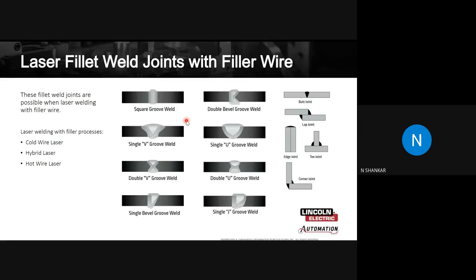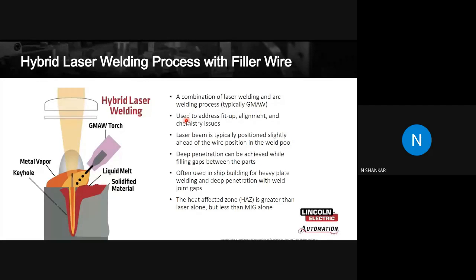You can do a cold wire laser or a hot wire laser with hybrid laser welding. When you say cold, you use a GMAW torch and you feed a wire. Conventionally it's called GMAW hybrid laser welding, where a combination of a laser arc with a GMAW wire is being fed. Both these together melt the base metal and then add the consumable to fill up the gap, and that's how you get a hybrid GMAW welding process. The heat affected zone is going to be definitely more than the laser welding alone, but